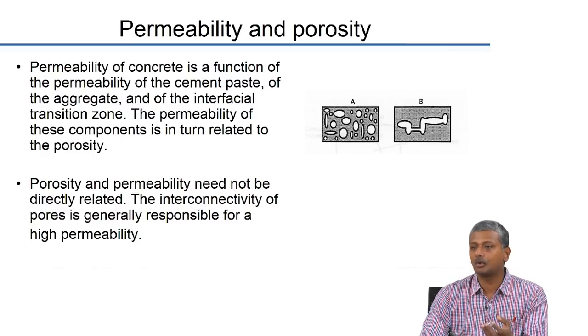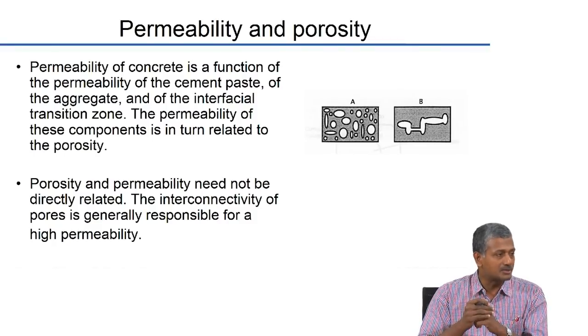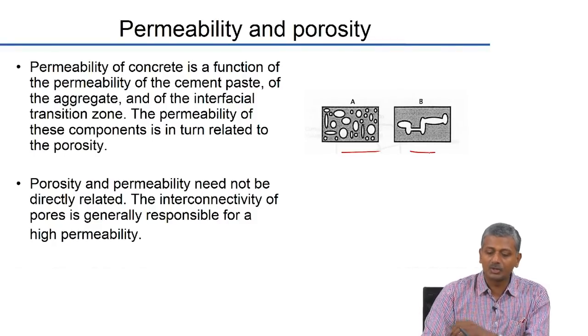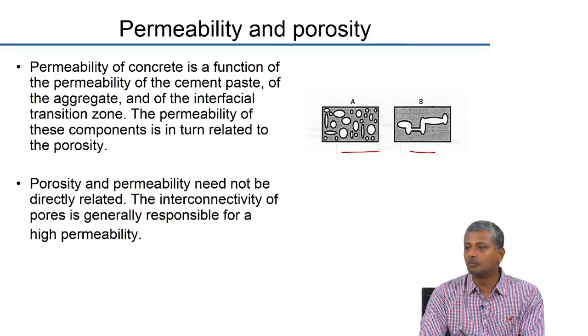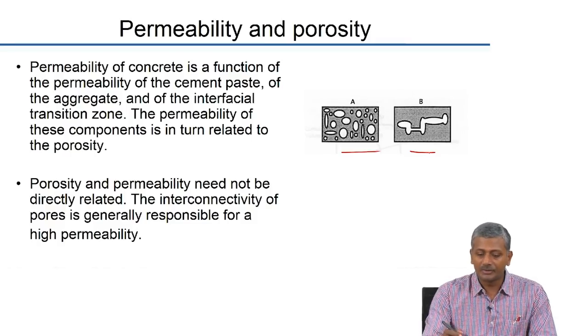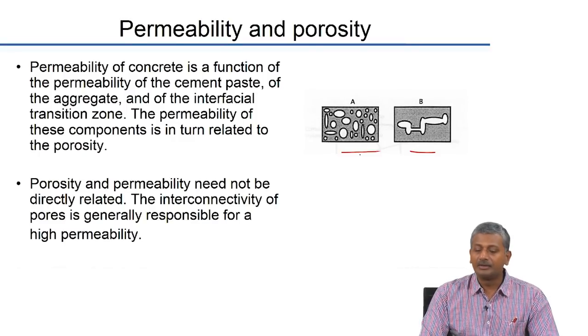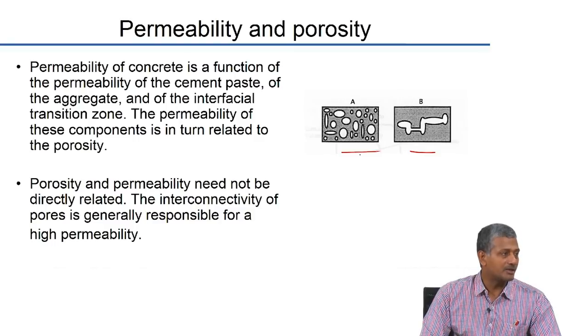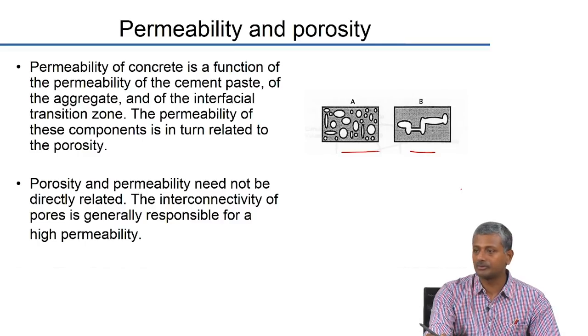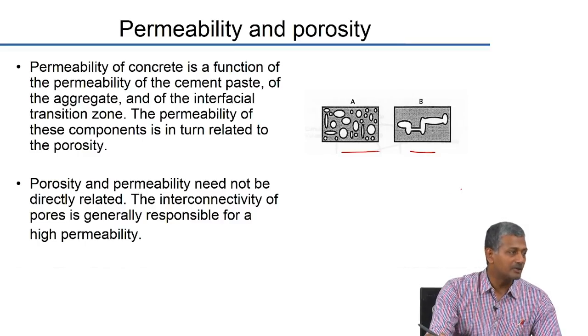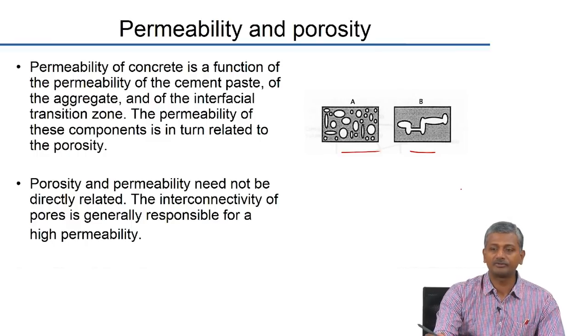You can design air entrained concrete with low permeability also, because these voids that are created because of air entrainment are mostly discrete. So, this picture on the right shows you typical understanding of what is meant by porosity and permeability. The system on the left, that is A, will have several pores, the porosity is high, but these pores are not really connected. System B, you only have a single pore which is completely connected throughout the structure of the system. So, you can expect that there will be greater permeability in the case of B.